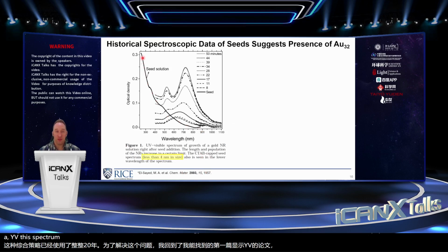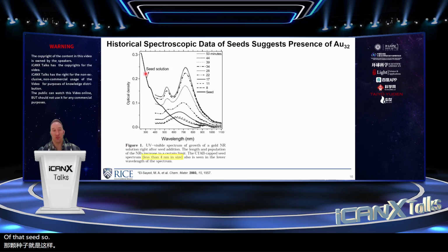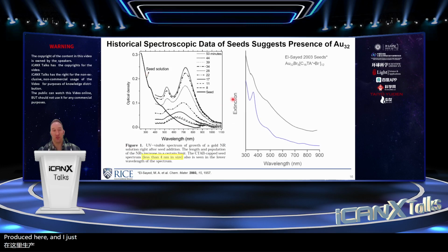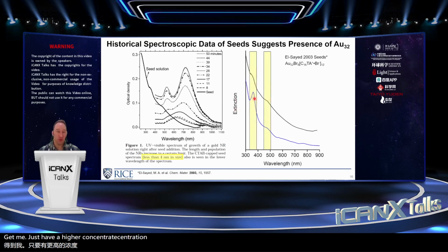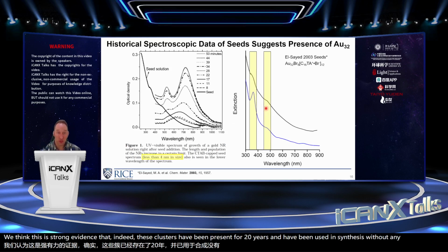a UV-Vis spectrum of that seed produced here. And then I just extract data and plot it out. We just have a higher concentration of gold-32. So the peak here is just more pronounced, right? It's a sharper peak. We can see it a little bit more easily. So we think this is strong evidence that indeed these clusters have been present for 20 years and have been used in synthesis without anyone really knowing it.